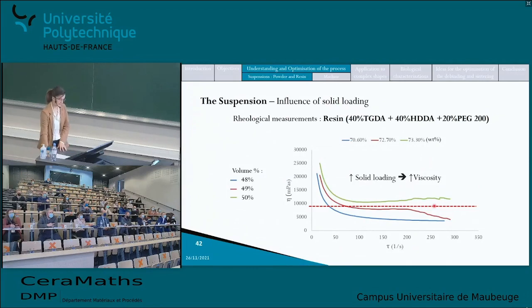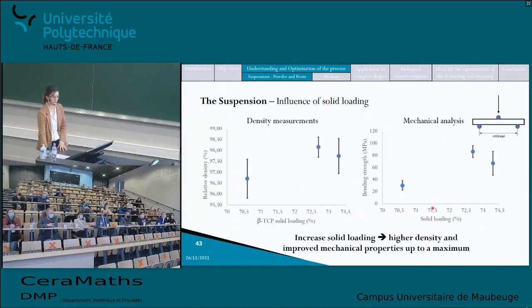And I did some density measurement and mechanical analysis with the 3-point bending tests. What appears here is that the increase of the beta-TCP solid loading seems to lead to an increase of the relative density and an increase of the bending strength, but up to a maximum. Here it is difficult to draw a really precise conclusion due to the error of measurement. However, the tendency that is observable with the density measurement is the same as that observable with the mechanical analysis. So we can assume that the increase of the solid loading provides a higher density and improves the mechanical properties, but up to a maximum.